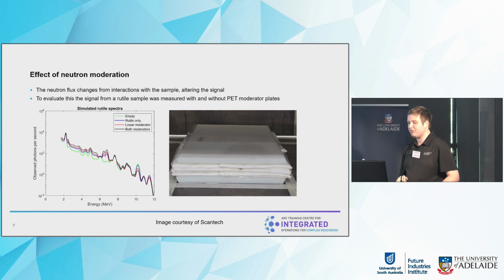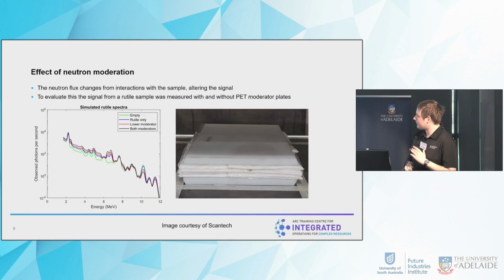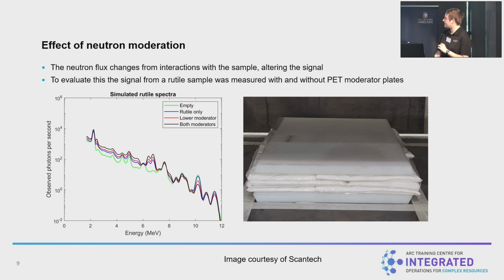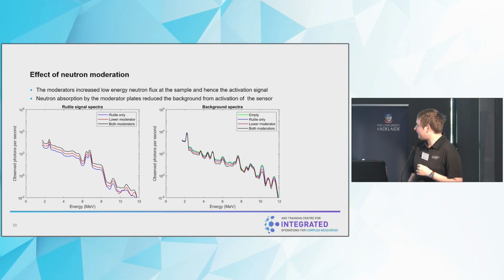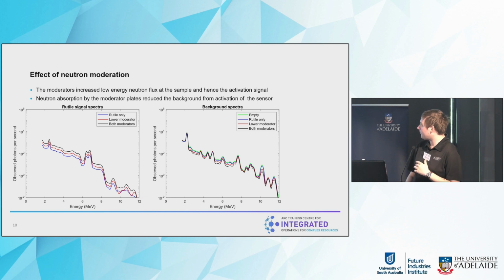The resulting signal is shown on the left, and we can see that the main titanium peaks located between 6 and 7 MeV are significantly increased with the addition of the moderation, showing that even with the same amount of material, it is possible by good design to help boost the measured response. This can be further illustrated by separating the signal from the background. As we can see on the signal on the left, there is a consistent increase across the entire spectrum, as the additional moderation boosts the low-energy neutron flux reaching the sample and boosts the measured signal by increasing activation.